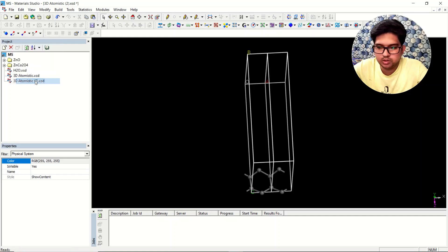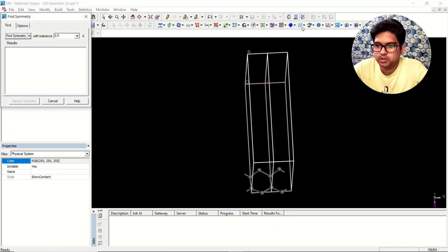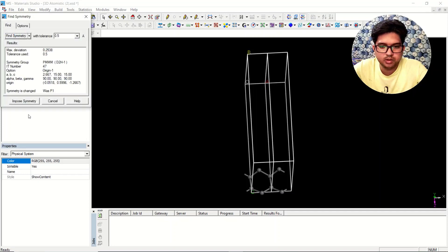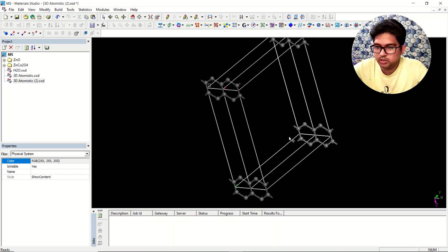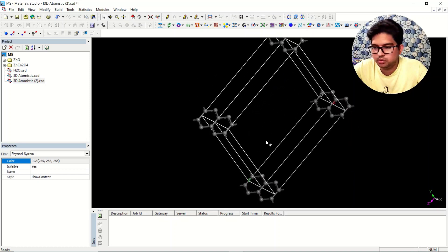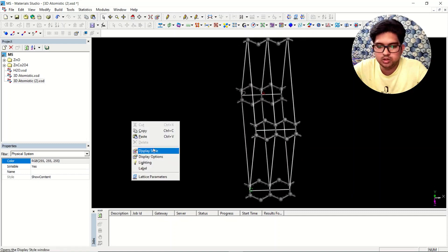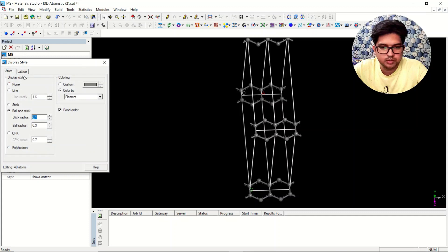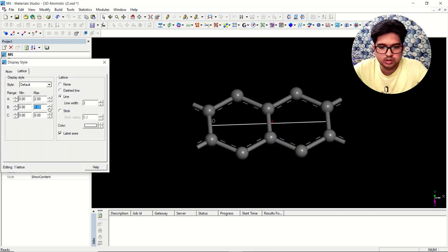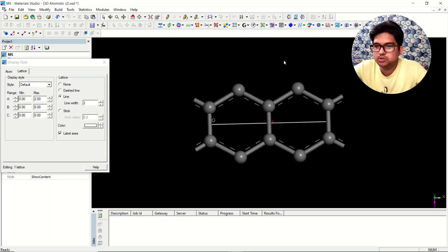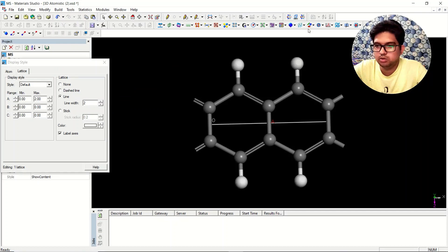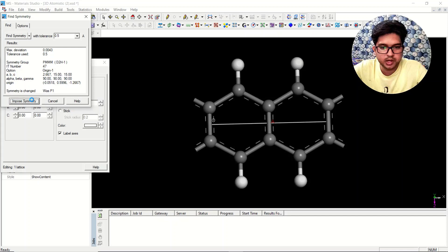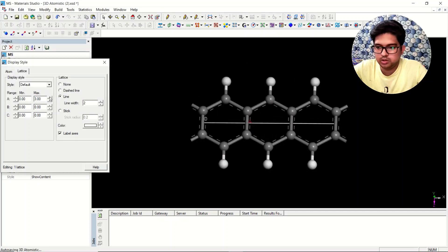We'll go to Monitor Bonding and you'll see this is getting connected. Press on this to get the proper symmetry. We also need to add hydrogens — don't forget that. This is a three-dimensional system but all layers are far apart, so we assume it is one-dimensional. Go to the lattice, set symmetry to P1, then go to Hydrogen, and it will automatically add hydrogens wherever required.